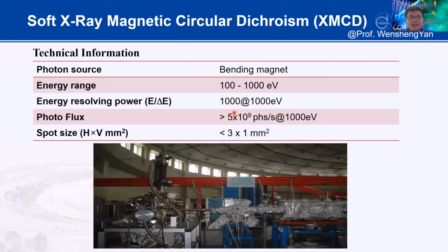This is the soft X-ray magnetic circular dichroism endstation, which we call XMCD or SXMCD. The photon source is a bending magnet. The energy is about 100 to 1,000 eV, and the energy resolving power is about 1,000 at 1,000 eV. The flux is not so high, optimized to about 5 times 10^9 photons per second. The spot size is also a little bit larger, about 3 times 1 millimeter square.